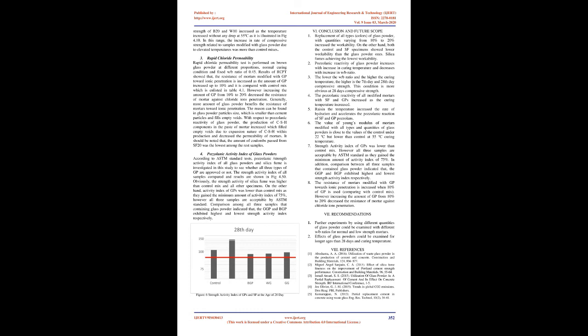3. Rapid chloride permeability. Rapid chloride permeability test is performed on brown glass powder at different proportions, normal curing condition and fixed W/B ratio of 0.45. Results of RCPT showed that the resistance of mortars modified with GP toward ionic penetration is increased as the amount of GP increased up to 10%, compared with control mix, which is enlisted in Table 4.1. However, increasing the amount of GP from 10% to 20% decreased the resistance of mortar against chloride ions penetration.